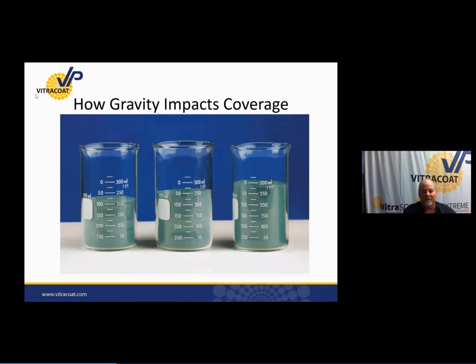The one in the middle has very little zinc, and the one on the left has enough zinc to give you some properties. The point is that while the zinc itself makes the specific gravity of the coating much heavier and you're getting less powder per pound, you need to have enough zinc to give its performance. The middle one illustrates that if I don't have enough zinc to give its performance, I'm just paying for something that gives me little coverage or a reduction in coverage because it's heavier.